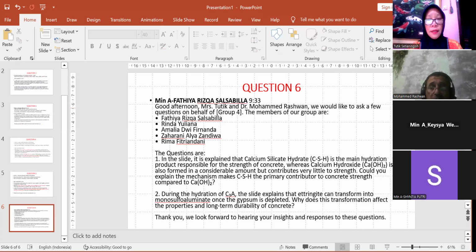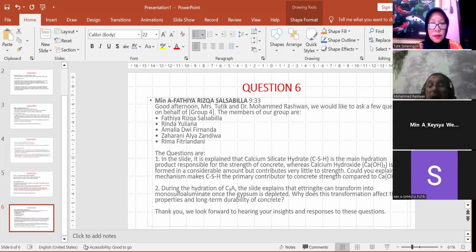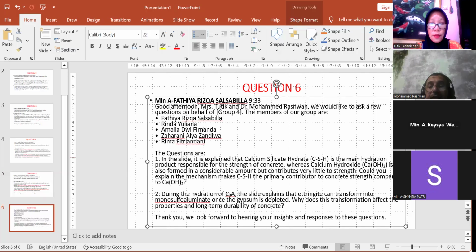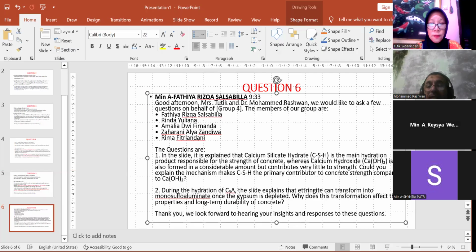The problem after that: if the concrete structure is put in a medium with another source of sulfate, like seawater, if we build a bridge or any structure in seawater or in soil rich in sulfate, the monosulfoaluminate phase will react again with the sulfate and produce what? Ettringite, the second time, but this second ettringite is produced when the concrete is hardened.